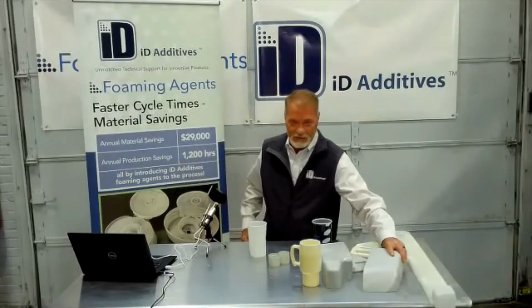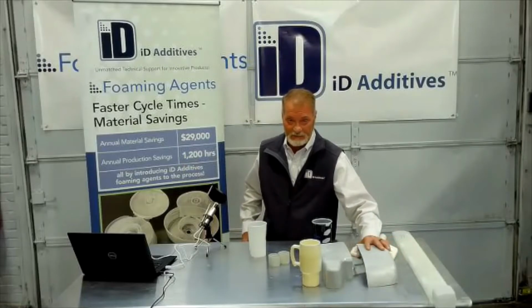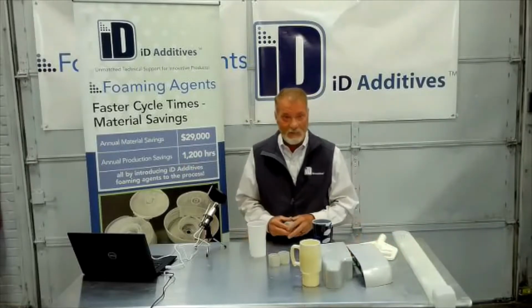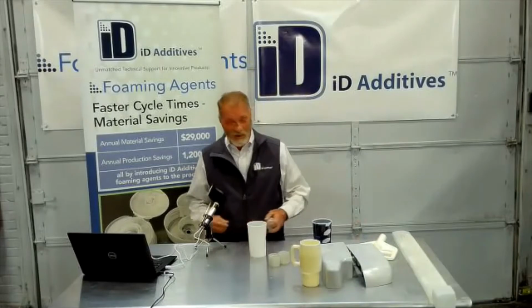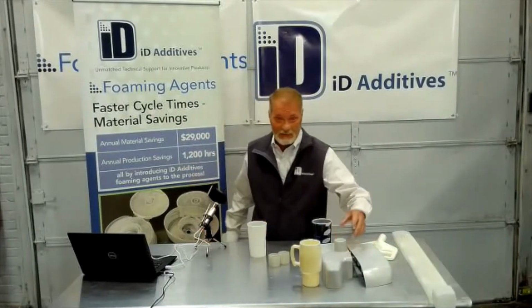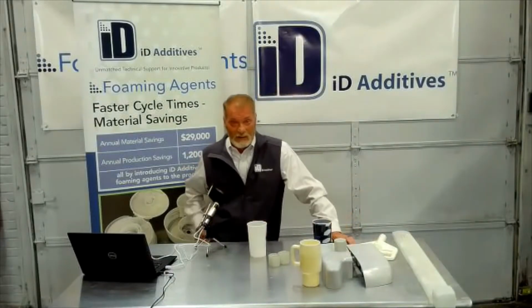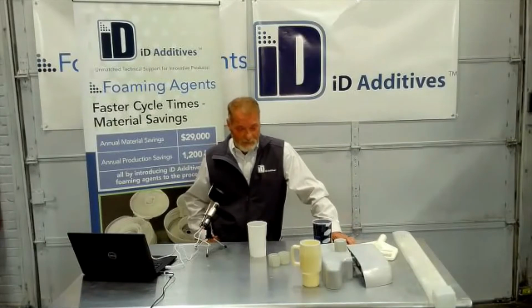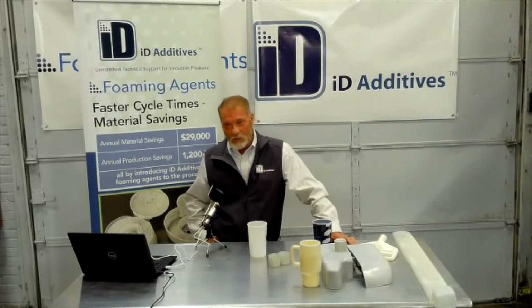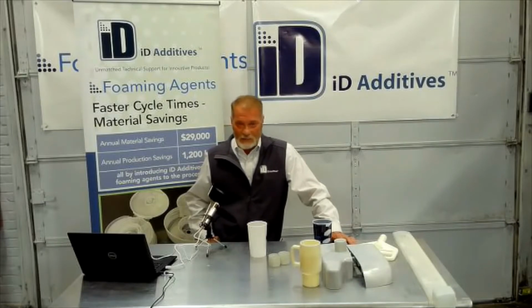But injection speed is the key. The faster you get it in, the more weight you're going to pull out. Now, you're obviously going to pull weight just by taking your pack pressure down. But the key to light weighting when it comes to foam is speed. So again, foam isn't for every application.